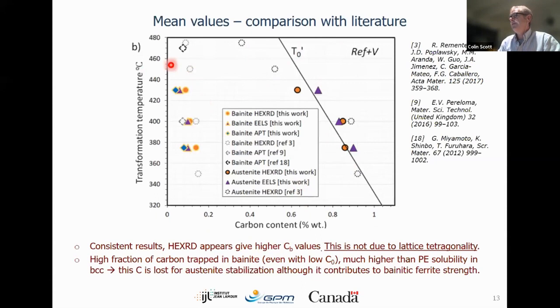One thing that we would like to look at further is the fact that all of the high energy X-ray diffraction data seems to give higher values for the bainitic ferrite carbon than the EELS or the atom probe techniques. So that's something that seems to be systematic and is quite interesting. All of the data that we've got so far predicts a high carbon content in bainite, even with these low nominal 0.2 carbon steels, much higher than para-equilibrium would predict. So this carbon is obviously lost for austenite stabilization, although it may contribute to bainitic ferrite strength, depending on whether it's clustered, precipitated, or in solid solution. In this study, we don't make any difference between the state of the carbon in the bainitic ferrite. We measure it all.